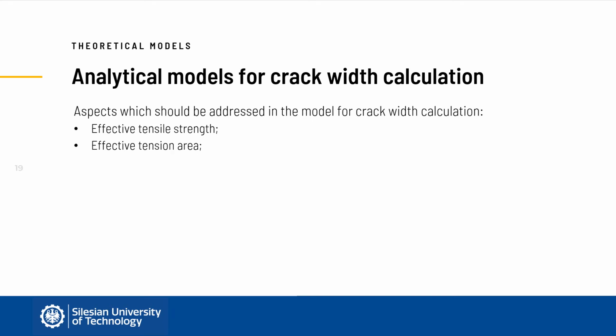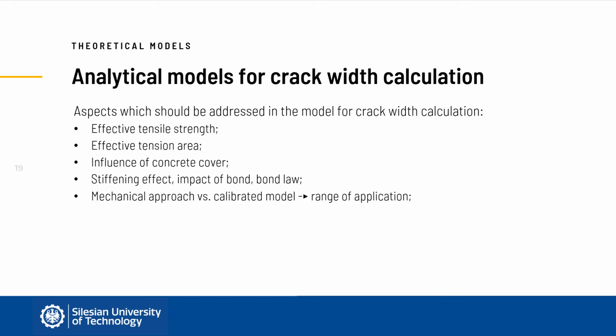The effective tension area, so the area of concrete section which is effectively engaged in transferring tensile stresses due to the limited range of impact of reinforcement. Influence of concrete cover. Tension stiffening effect of steel due to the bond between steel and concrete, and an appropriate bond law to represent this behavior. Whether the model is based on the mechanical approach or calibrated, which will limit its range of application to the cases based on which it was derived.